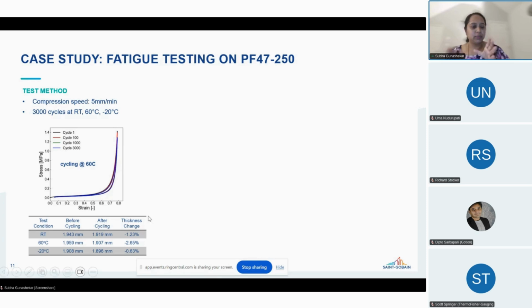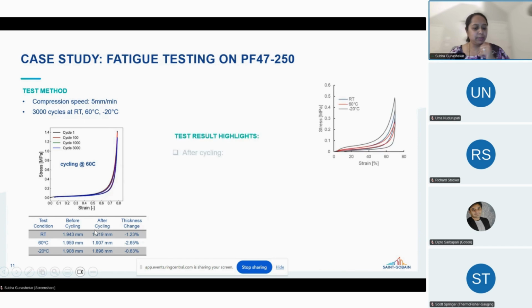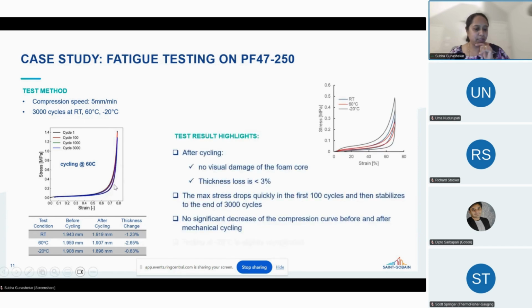So we did this test at room temperature, 60 degrees, and at minus 20 degrees. So we did cyclic fatigue tests and measured the thickness before and after. And we also measured the stress strain values. And you see this curve here is just at 60 degrees Celsius between cycle 1 and cycle 3000. There was a little bit of a drop between the first 100 cycles because it's a polymer material, so there is some lag there, but it's very resilient. But after the 100 cycles, it did not grow. The hysteresis is much shorter.